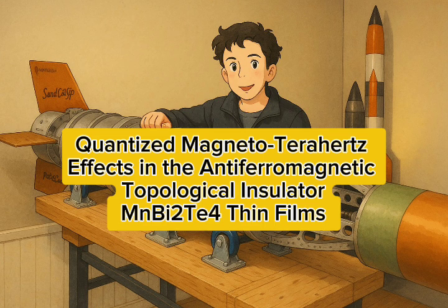What does that signal indicate? A transition to what's called a canted antiferromagnetic state, or CAF. The magnetic moments in the layers are no longer perfectly anti-aligned. The external field starts to pull them, making them tilt or cant slightly towards the field direction. So they're not fully aligned, but not perfectly opposed either. Like they're leaning. Exactly. This canting means the cancellation isn't perfect anymore, leading to a small net magnetization, which causes the Faraday rotation. For example, at 3 Tesla, 0.4 terahertz, it was about 1.6 milliradians.